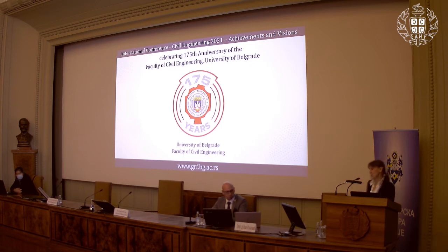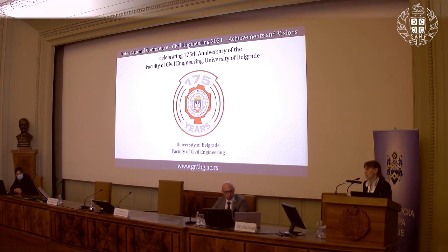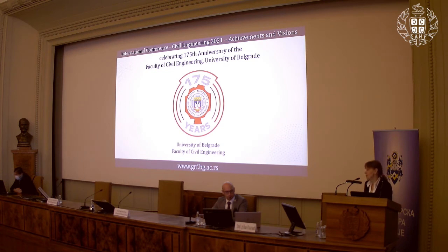And these concretes are called high volume fly ash concrete, recycled aggregate concrete if you use recycled aggregates instead of natural, high filler content concretes, and so on. But if you speak about geopolymers, we tried at our faculty with such type of concrete, and we also were not successful very much. This is for the public. This is a type of concrete in which the whole amount of cement is replaced with, let's say, fly ash or some other type of mineral addition. But if you use fly ash, then you have to heat the concrete, and this is the reason why we thought that it is not applicable to on-site structures, only for precasting.